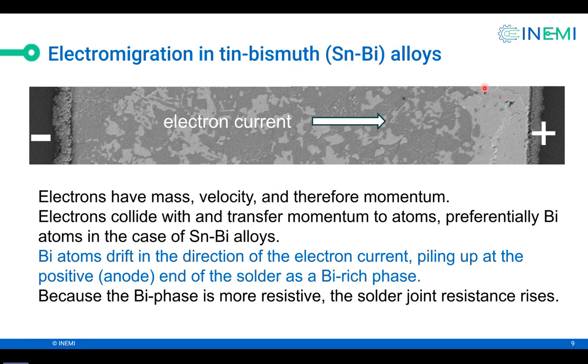Now, bismuth has high resistance. So when the bismuth phase collects at the anode, being of high resistivity, the overall resistance of the solder joint increases. So we can measure the electromigration by measuring the resistance of the solder joint. So that's the theme of the project, to observe electromigration by measuring the rate of change of resistance, or rate of increase of resistance, of the solder joint.